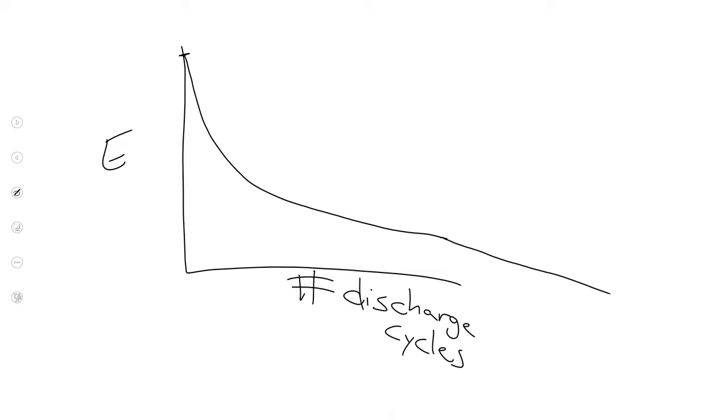My friend's research was actually on a process they discovered at the University of Colorado that allows you to put down basically layers of atoms. They were looking at aluminum oxide, which is not a conductor. So it's not great, but it could kind of function as a salt bridge a little bit if it were only a couple of atoms thick. They found this process that allowed them to really reliably and uniformly deposit a three-atom-thick layer on top of the cathode of a lithium ion battery, which drops your initial energy density, but then it stays almost constant.